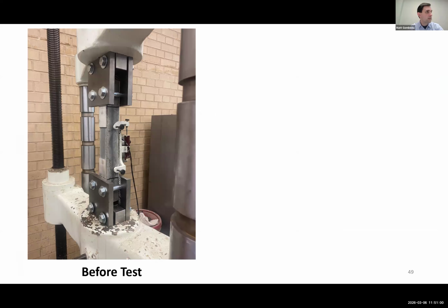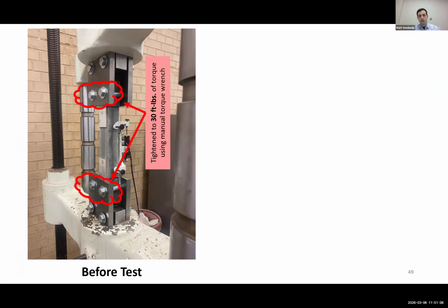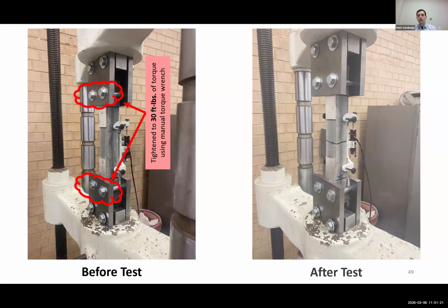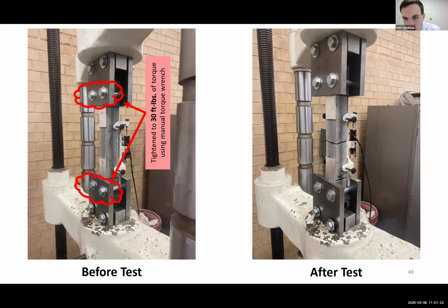So you can see here on the left, there's a specimen loaded in the machine. It's got the grips at the top with 4 bolts. Those are tightened at 30 foot-pounds of torque using a manual torque wrench to ensure the right tightness. And then you can see there's a transducer there that'll measure the displacement at the middle of the member that we can then calculate the strain from. And you can see here on the right, after the test, if you do the test right, you get this crack right in the middle of the gauge length of where the transducer is.